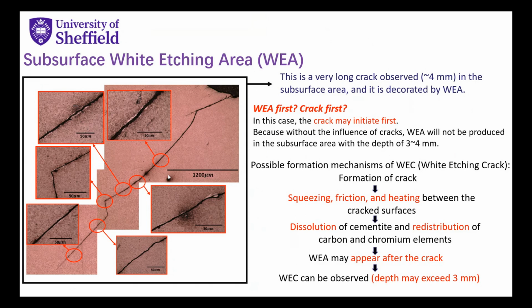So in this case, I believe the cracks initiate first, and because of the formation of cracks, there may be some very complicated reactions between the crack surfaces, maybe squeezing and friction and heating between these crack surfaces. And then we have the dissolution of cementite and the redistribution of carbon and chromium elements. Then we have the white etching area along these cracks, and that is the so-called WEC in this specific bearing.